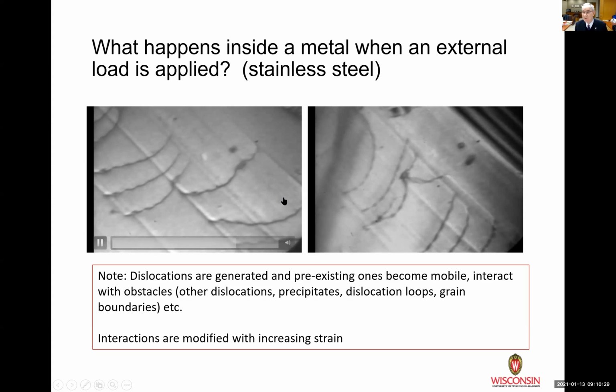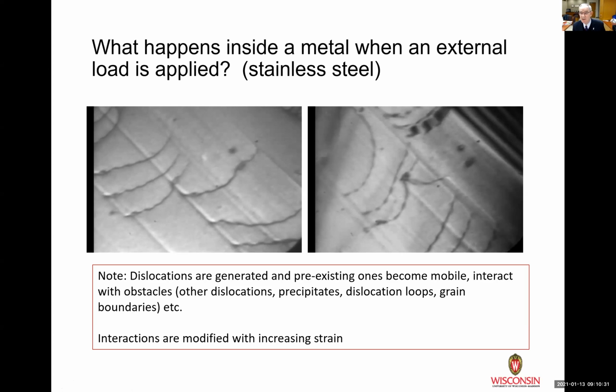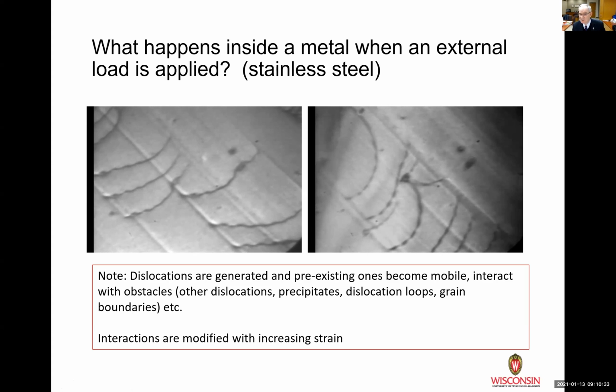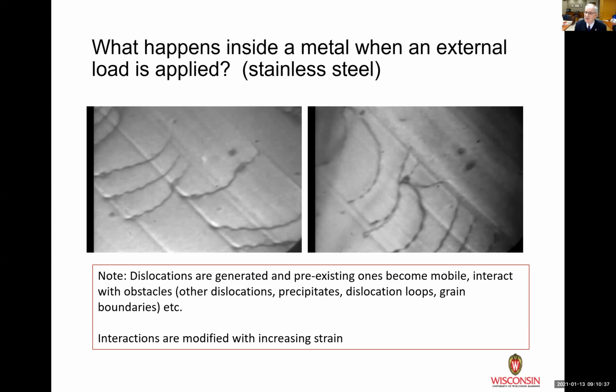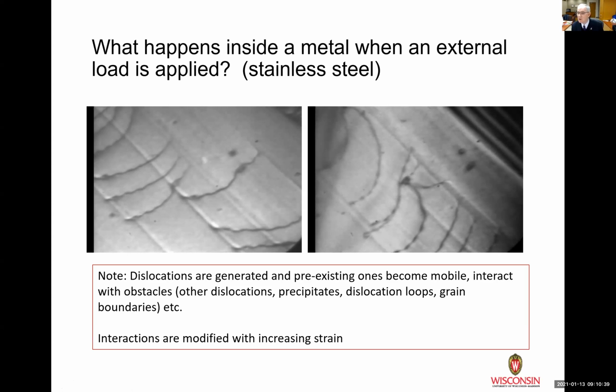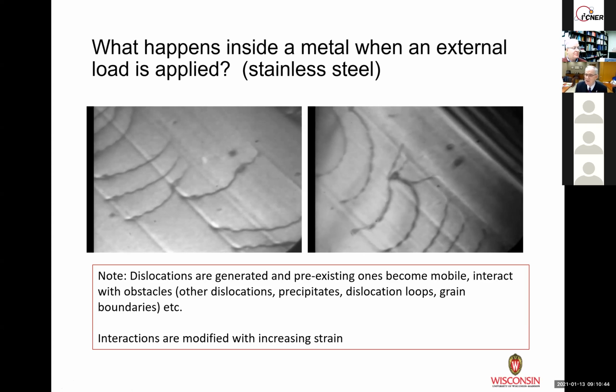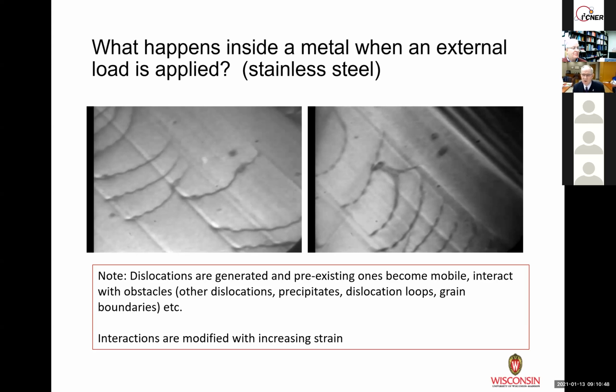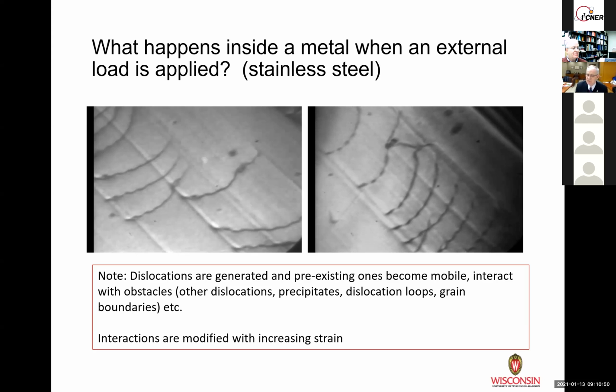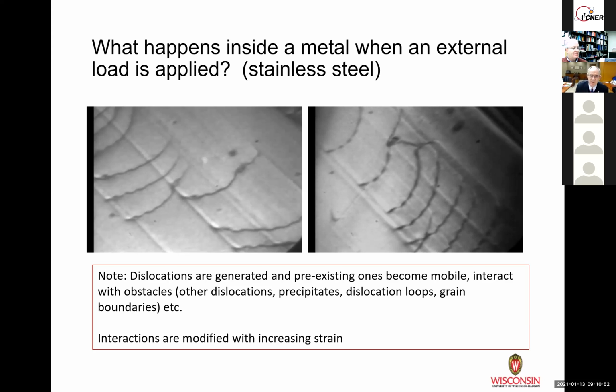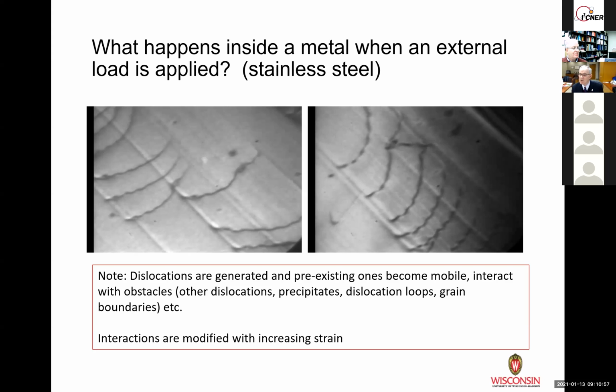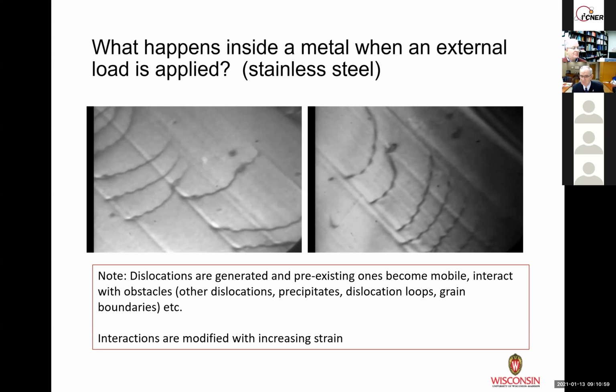It's the same particle, same dislocation types, but hopefully what you're seeing is that the dislocation is now pinned longer at the obstacle and is in fact breaking past the obstacle in a different way. So the question you should be asking yourself: if the precipitate didn't change, if the dislocations didn't change, what was responsible for the change in the interaction?